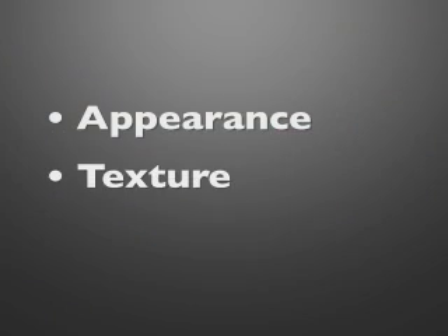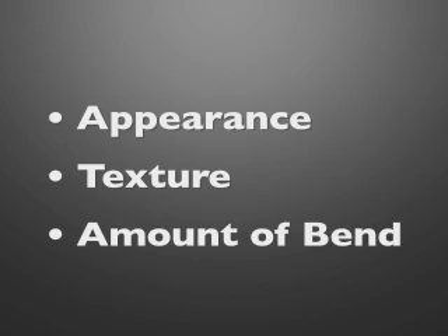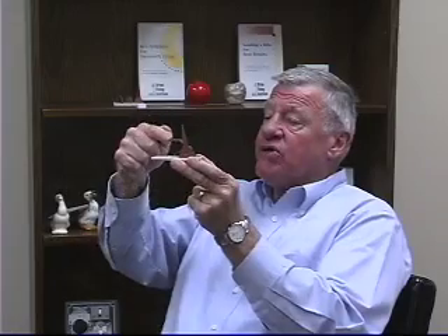After firing, we should obtain the cone and look at it for the appearance, the texture, and the amount of bend that actually occurred within a cone. We should take this data and information and then log it into a book so that we can have the assurance of consistency and reproducibility within the firing, and then possibly look at it for potential firing problems that can help us down the road.